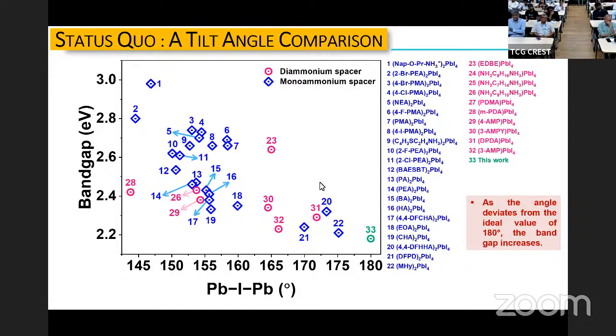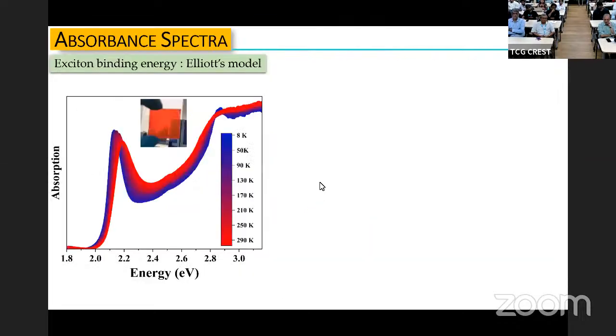That is the ideal. You cannot get more than 180 degrees, because if you keep going past 180 degrees, you actually get a smaller angle again. So that's the largest angle you can get. And as the angle approaches 180, you can see the band gap is decreasing. And fortuitously, we have been able to get the only example of an ideal 180 degrees realized in a Pb-I-Pb angle. And I'll come back and talk about why this one gets to 180 degrees in a moment.